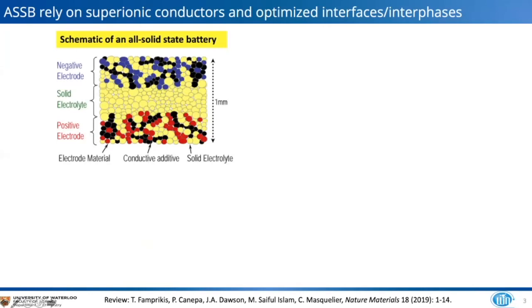So the concept is pretty simple. We have a positive electrode at some high positive potential, which is indicated here by red. We have a conductive additive, typically carbon, indicated in black. And at the negative electrode, we have the negative electrode material indicated in blue, again with some electronic additive. And the electrolyte runs completely through that cell.